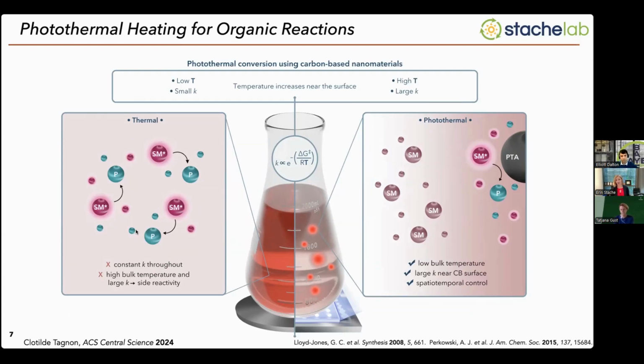But in doing so, you're also going to increase the rate of other reactions, other side reactions, which can complicate your product streams. But in photothermal conversion, because of the unique heating mechanism, you're only generating these thermal gradients near the surface of the particles. So instead of having this bulk solution all at one temperature, most of the solution will be at ambient temperature, and you'll have these localized hotspots where the particles are absorbing light and converting it into heat. So what that means is that most of the starting materials in the reaction mixture will not be doing anything, but the ones in proximity to the photothermal agent can undergo the reaction at a very fast rate because this temperature can be much higher than what you have in the bulk solution. And so when you have this idealized photothermal conversion system, you can promote very high activation barrier reactions with high selectivity due to these local thermal gradients.